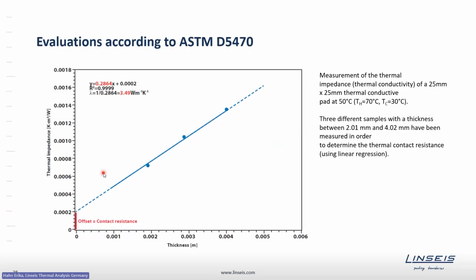Because of that, the typical testing procedure is the following: we measure 3 different sample thicknesses where we obtain the thermal impedance, plotted in a way like that. Having the thermal impedance in dependence on the sample thickness, we find that it's a linear relation, as for each sample thickness, the same contribution is the contact resistance. This corresponds then to the offset on the y-axis, and the inverse of the slope of this linear relation corresponds to the thermal conductivity of the material without the contact resistance. So that is a typical measuring procedure. Here you can see an example of a thermal conductivity of about 3.5 watt per meter Kelvin, and we found out here as well the contact resistance.